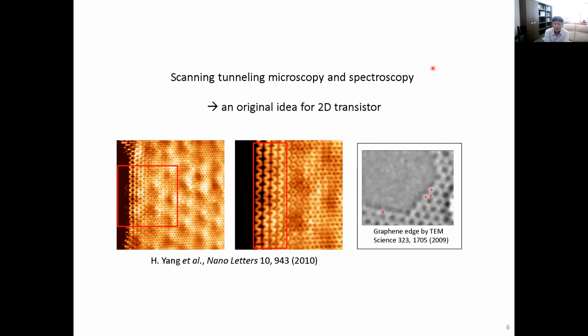So I already mentioned I did my PhD with STM, scanning tunneling microscopy, and these are some of the images. They are graphene edges, armchair edges. Of course, these days, many strong TEM groups are reporting these graphene edges by TEM, for example. But when we think about devices, devices are playing with electrons near the Fermi level, low energy electrons. For TEM, we can see the lattice structure very well. But if we look at the Fermi electrons, the electrons very close to the Fermi level, we see how the wave function of the electrons are formed near the edges.